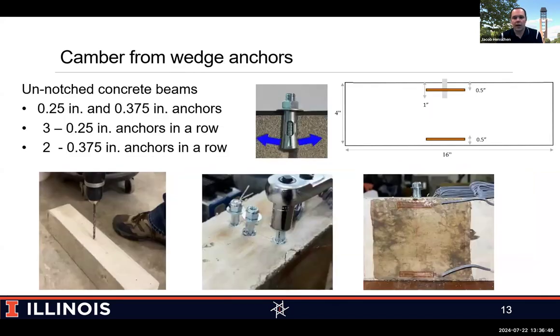And so then let's go to our anchors, where again, it's really difficult to actually back out what that expansive force is as you tighten the anchor. And so we use 2 different types of anchor, or 2 different sizes of anchors. They really are the same type. They're these wedge shaped anchors, and that picture in the middle there shows you the force they're exerting on the surrounding concrete. And for this, we started with just a gauge on the top and the bottom, where that top gauge was going to be right where that bell flaring would be for our anchors.